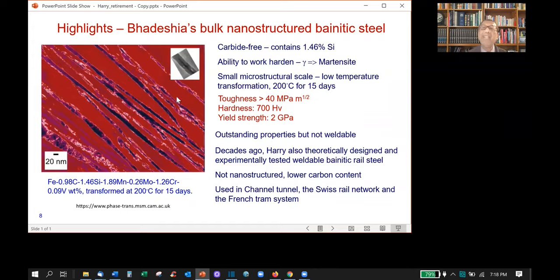And what sort of fineness can one expect? This scale is 20 nanometers, and the inset here shows a carbon nanotube, and the diameter of this carbon nanotube is between 20 and 40 nanometers. So these thicknesses are of the same order of magnitude. This special microstructure and the fineness of the structure give excellent properties that are shown here in the red. So the properties are outstanding. It's the first nanostructured alloy that is made in bulk, but this alloy is not weldable because it contains about 1 weight percent carbon. It cracks.